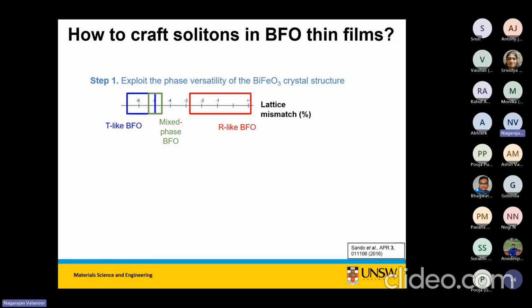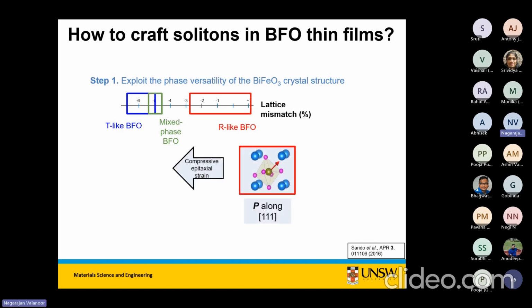We said that if you have R-BFO, which is the bulk rhombohedral structure, which is already tilted, right? You put tensile strain on that. These guys from Berkeley tried to do it on DSO. They already used tensile strain. It is going to just make more, actually forms very nice stripe domains. So the first idea is that instead of tensile strain, push the vector out of plane. So make it closer to 0, 0, 1. How can I do that? You use lanthanum aluminate substrate.